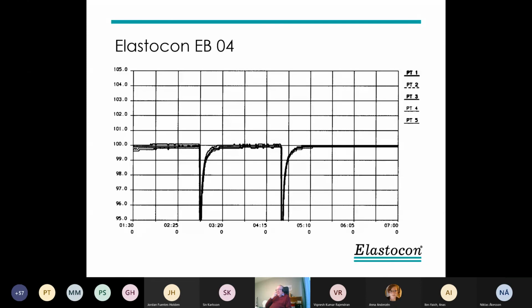Here is our own cabinet oven, where we have a difference of plus/minus 0.2 degrees, and the last part of the curve is plus/minus 0.1 degrees. And that is in the range of the measurement error.